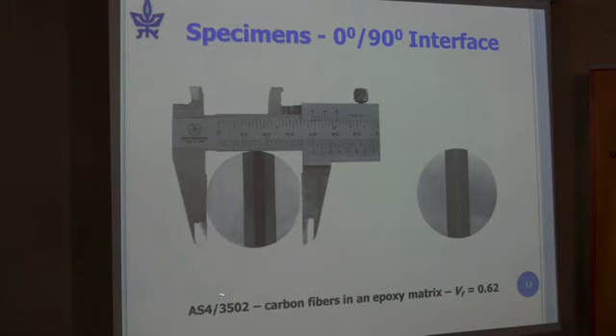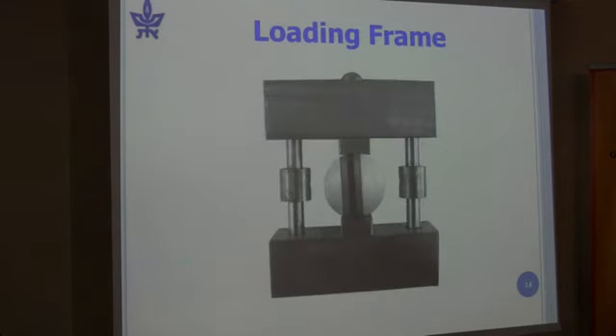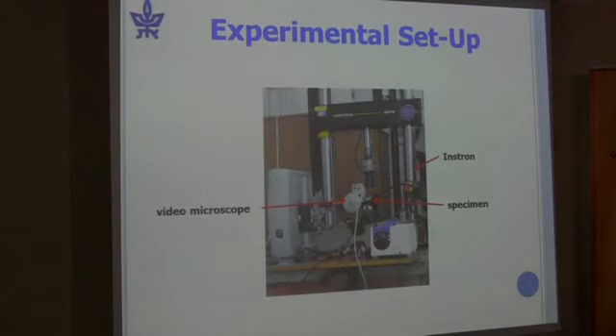The material used was AS4, which is a carbon fiber in 3502 epoxy matrix, and we had a volume fraction of 62% of fibers. And here is our loading frame. So as we rotate the specimen and we load in this direction, we get a whole host of mixed modes. So it's a very convenient specimen.